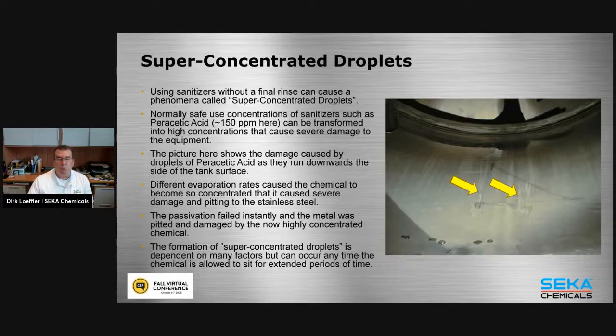Want to quickly talk about the super concentrated droplets. So this is a phenomenon I came across the first time at a large brewery in California, and we were actually just doing an audit, looking at tanks, and we opened up the tanks, and we observed this drop running down the side of the tank, and we noticed as this drop was running down the side of the tank, it was creating a pitting in the tank surface. So we did some more research on this, and it turned out that we were actually dealing with a phenomenon that is called a super concentrated droplet.